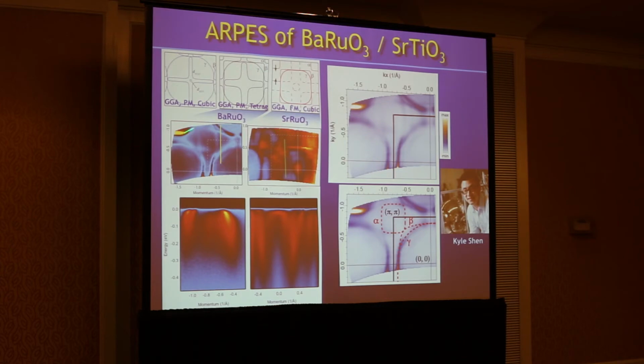And by having a pristine surface, I should mention that even at 180,000 atmospheres, even if you could make a large single crystal, it doesn't cleave. But here, in making a thin film of it, we stabilize the polymorph, and we have a nice smooth surface. So by looking at that in situ and not exposing the surface to air, we can look at the electronic structure, and we can compare the electronic structure to first principles calculations.